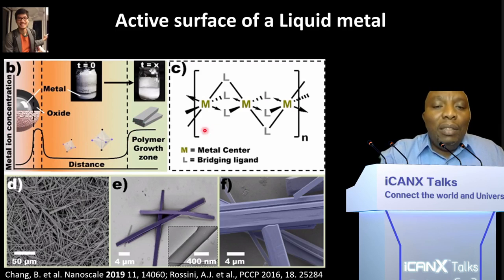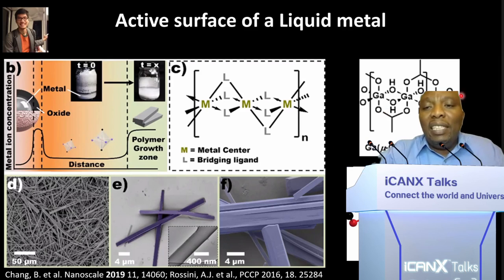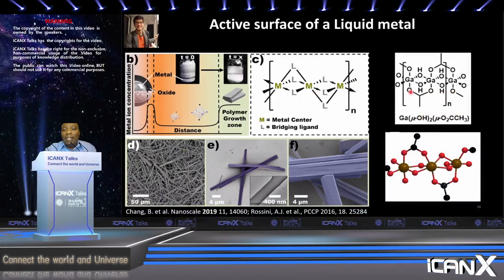The metal we chose to target here was gallium, our bridging ligand was the acetate, and a complementary ligand was hydroxy. So we were using aqueous solutions where the adducts were not very soluble. When we did that, this is the structure we ended up with. We had gallium metal centers with interloping acetate units and OHs occupying one plane. The interesting thing with this structure is that it had a little twist to it.